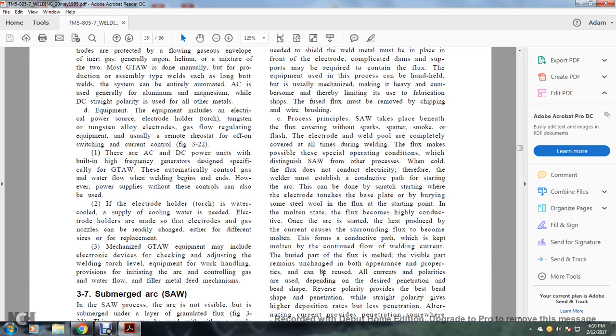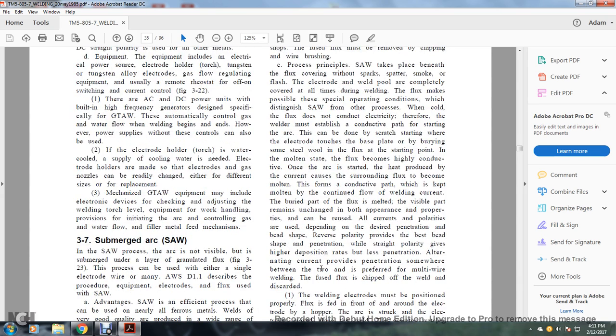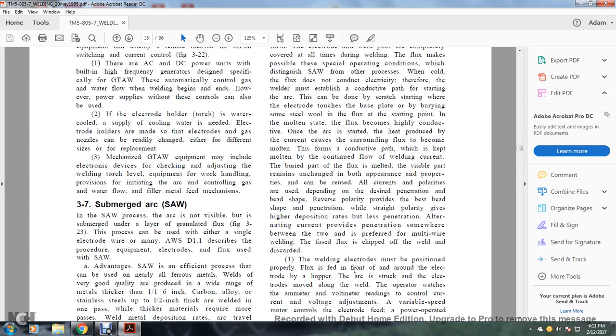All currents and polarities are used to bring on the desired penetration. Reverse polarity provides the best bead shape and penetration, while straight polarity gives higher deposition rates, but less penetration. Alternating current provides penetration somewhere between the two, and is preferred with multi-wire welding. The fused flux is chipped off the weld and discarded.